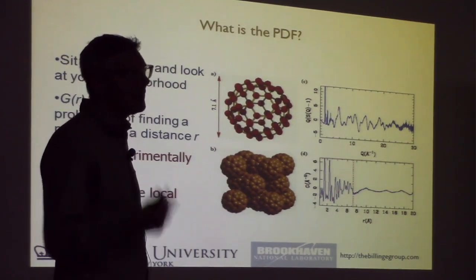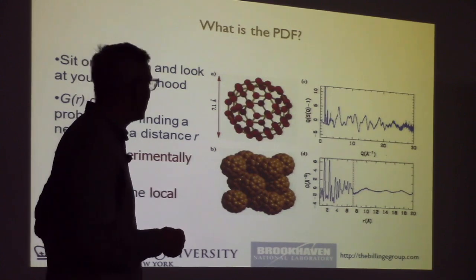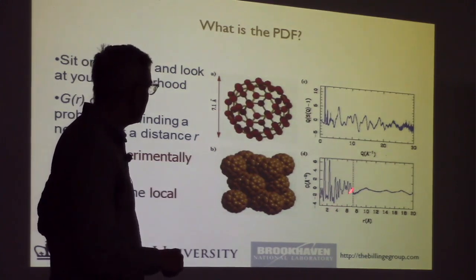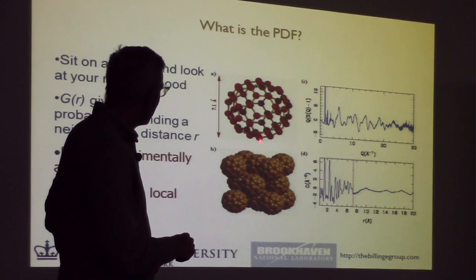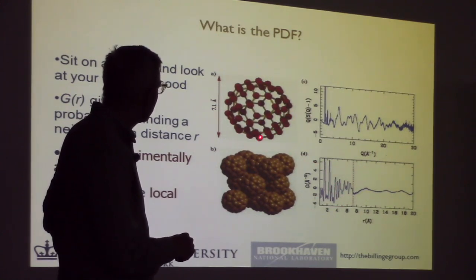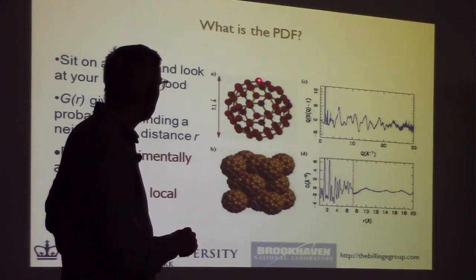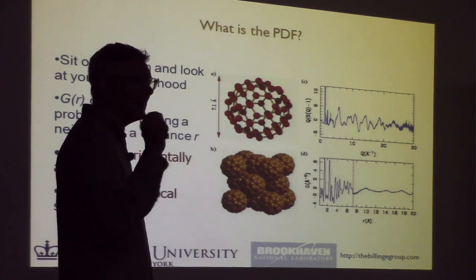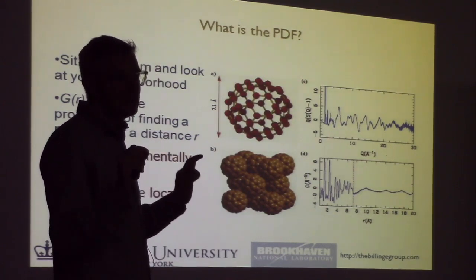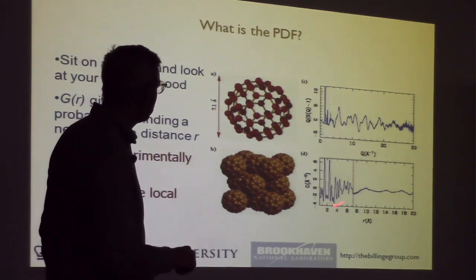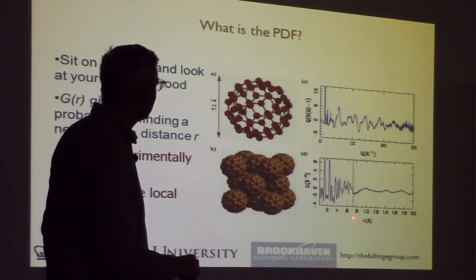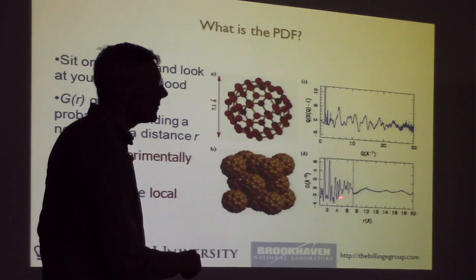But if you have a structure model for your material, like C60, you can compute all of these peaks. And the last sharp peak is the diameter. So I'm sitting on this atom, and I'm looking at that atom. It's exactly the diameter of the ball. And the ball is 7.1 angstroms. And that last sharp peak there is exactly 7. That's a 6 and that's an 8, so that's a 7.1 angstrom.